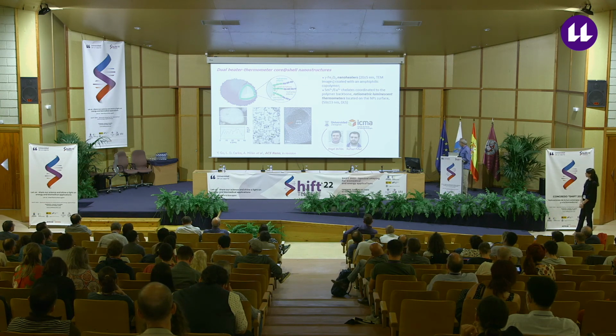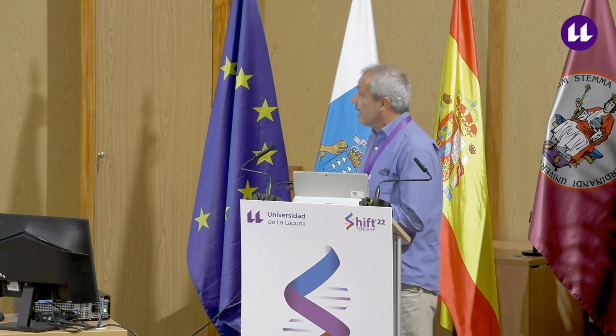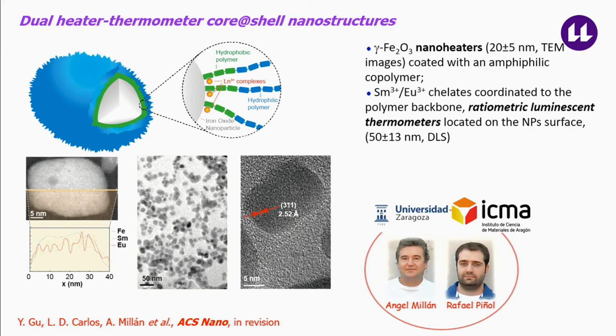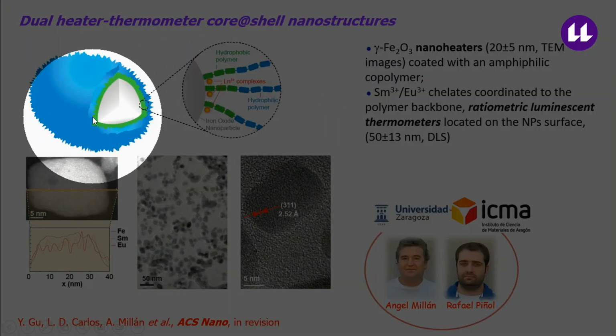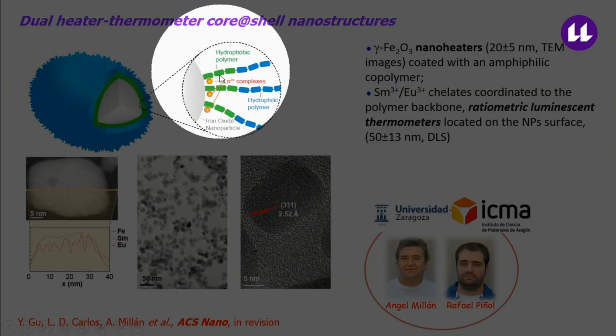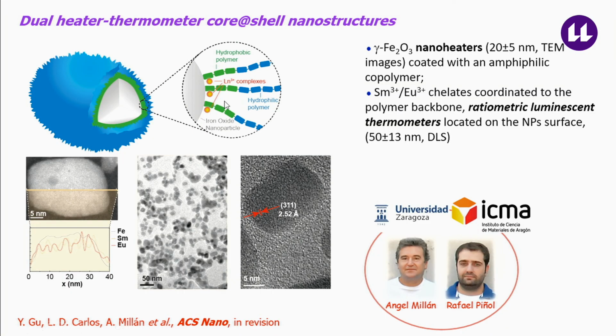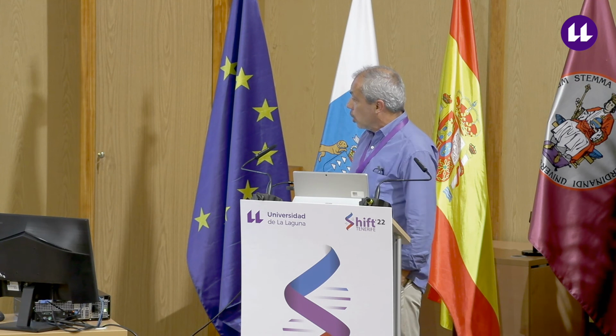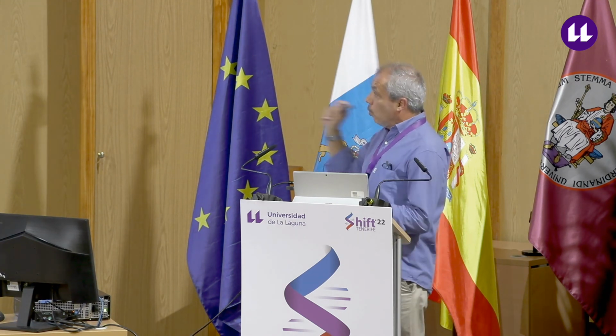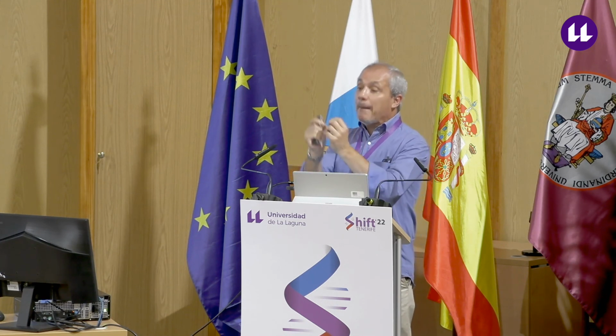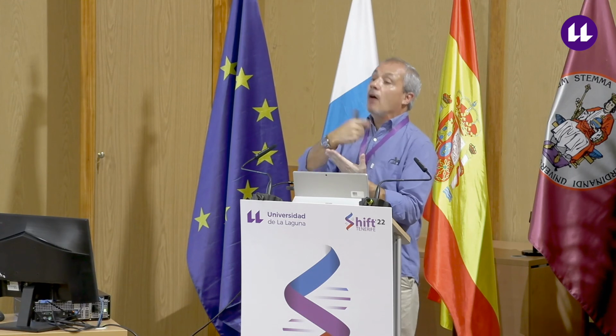No, yeah, this is that paper that I mentioned, which is now in revision, but we are fighting with the referees, and I'm not sure if we will be able to publish the paper, at least in ACS Nano, but let's see, because one of the referees doesn't believe at all in our results. But in this case, we have the magnetic particle, the core, okay, and then the complexes are located at the surface. And we found, due to the fantastic job done by Rafa, a system in which the magnetic field does not alter the luminescence.